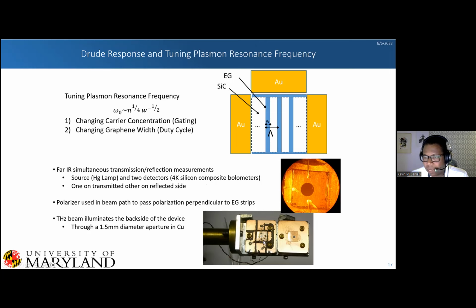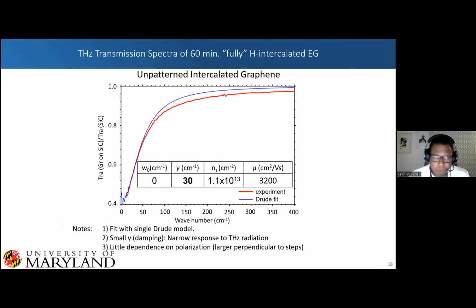So we would first grab just a bare silicon sample and do this test, and then we'll have our silicon carbide sample, and then we would do a silicon carbide sample with our structures, our graphene structures. And so the very first thing we looked at is an unpatterned graphene sample.